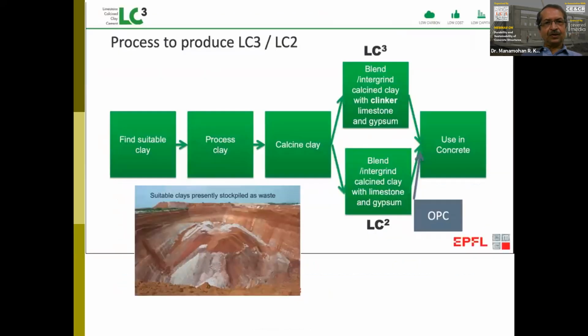And the process basically consists of finding suitable clay, processing the clay, calcining the clay, and then you can make either LC2 or LC3. If you blend the clinker with the calcined clay and limestone, what you get is LC3. If you blend only calcined clay and limestone and keep it as a powder, it's called LC2, which later you can blend with OPC and use in concrete.